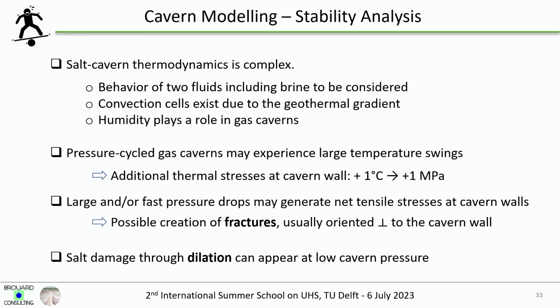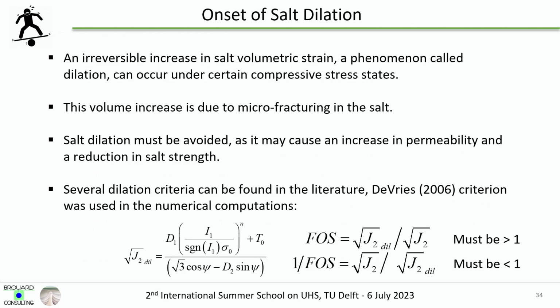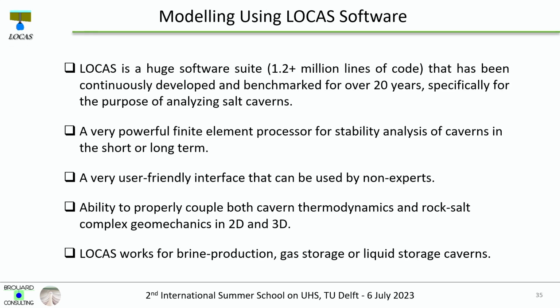When you have the swings of temperature, you trigger some thermo-elastic stresses, and you can get a frac, to be simple. A 1 Celsius variation of the temperature gives 1 MPa of additional stress, so you can get a frac. Also, when you go down to the minimum pressure, you can get some dilation. And dilation was presented yesterday. This is a kind of microfracturing, an increase of permeability of salt. I have no time to describe this.